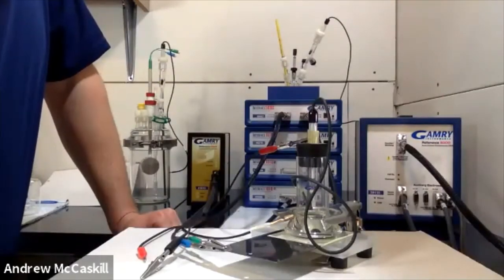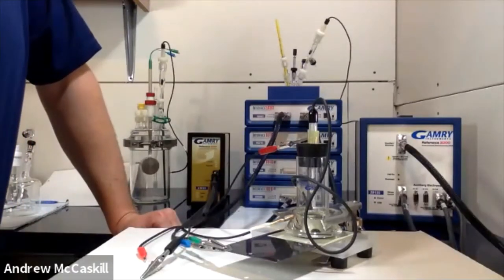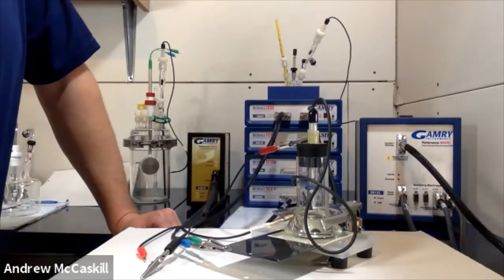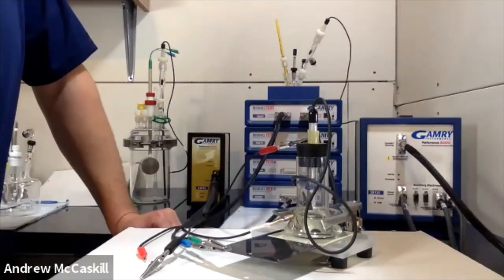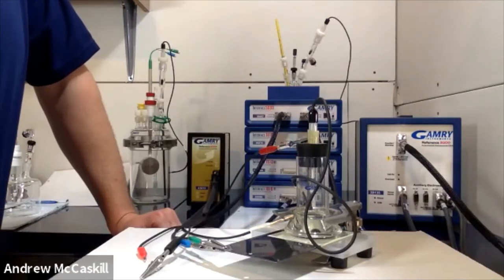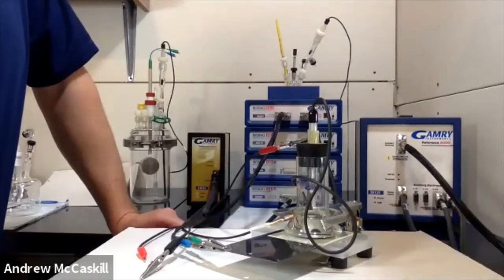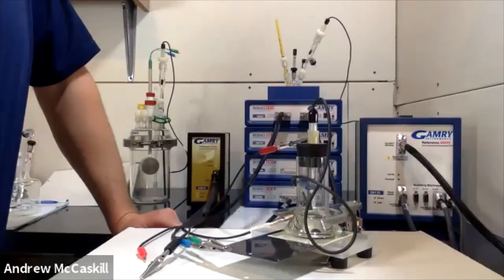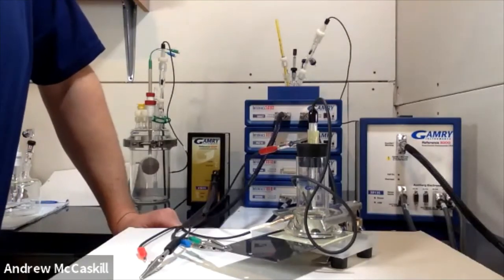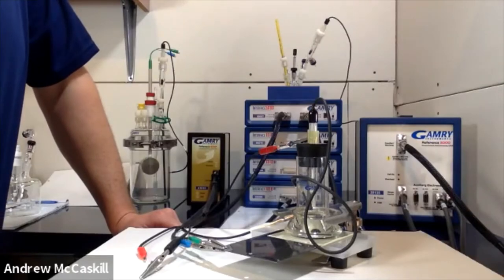So the kind of applications you'd use for this, of course, would be coated samples. With a coated sample, you could have this setup running probably for days, weeks, months, and collect good data. If you wanted to use a more corrosive surface, bare steel, something like that, that's certainly gonna corrode relatively quickly, then this cell would be very good for a single experiment, running something like linear polarization resistance, or a potentiodynamic scan, EIS, impedance spectroscopy. You could run those experiments and this cell would work very well for that.